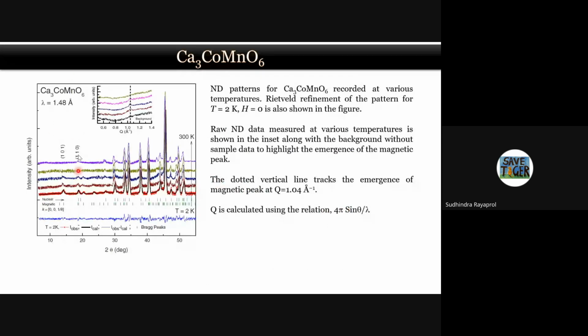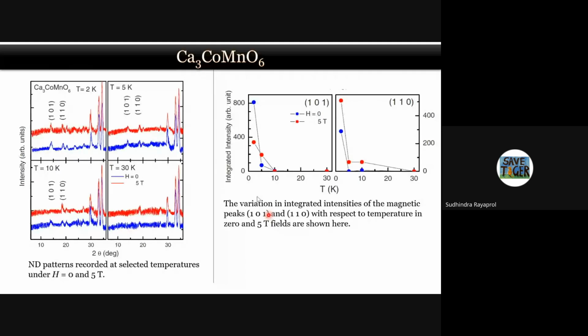So we wanted to see it through neutron diffraction. We carried out neutron diffraction as a function of temperature, and we find that there is a magnetic order present. It's a long range magnetic order again. So we are able to determine the magnetic structure of that. Now, along with neutron diffraction in zero field, we can do neutron diffraction with field also. And we find that the intensity of the magnetic Bragg peaks changes when you apply magnetic field.